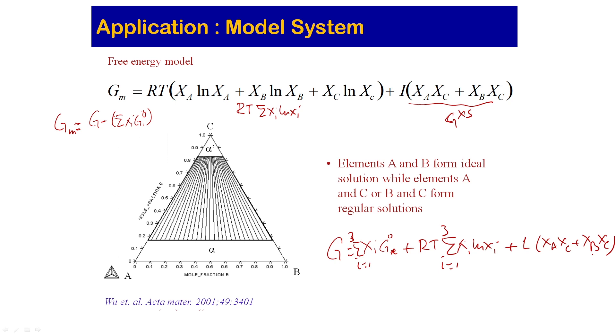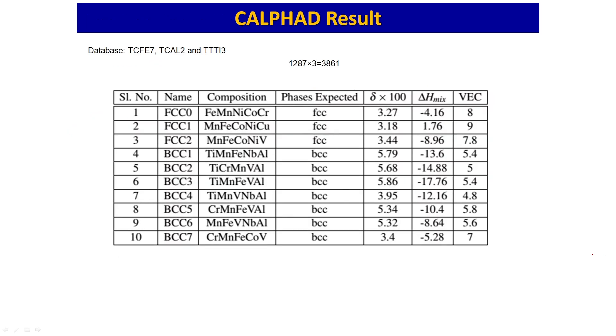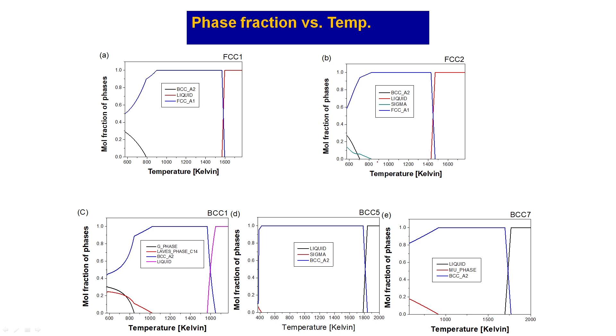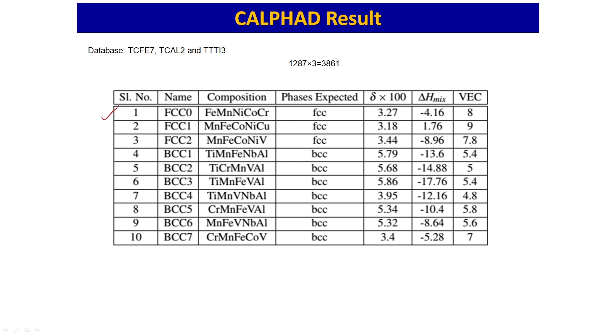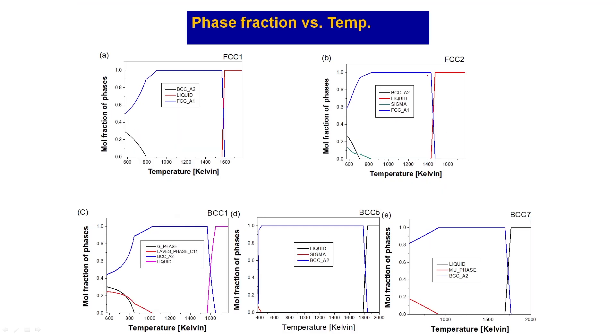For multi-component systems such as iron-manganese-nickel-chromium-cobalt — a standard high-entropy alloy system — we know the expected phases are FCC and BCC. One can calculate the enthalpy of mixing ΔH_mix using parameters such as valence electron concentration and atomic size differences (delta). Thermodynamic calculations using this CALPHAD approach can yield phase fraction versus temperature plots, showing three phases — FCC, liquid, and BCC — for a given alloy composition.